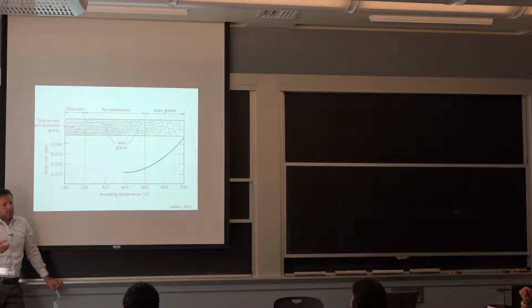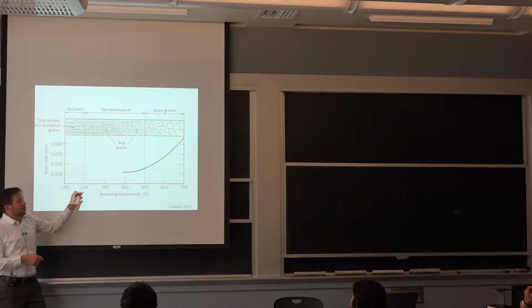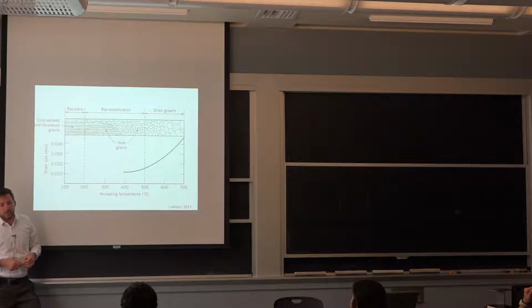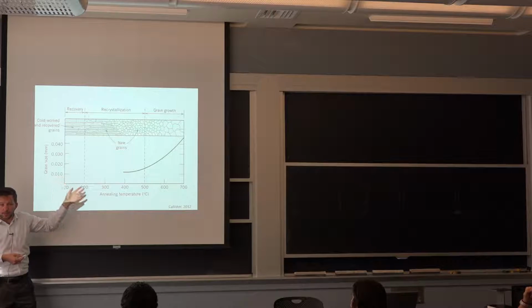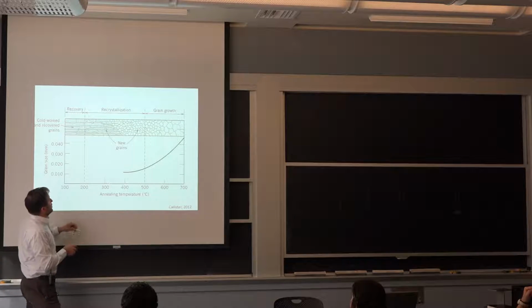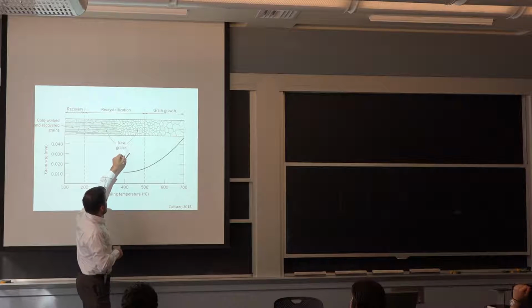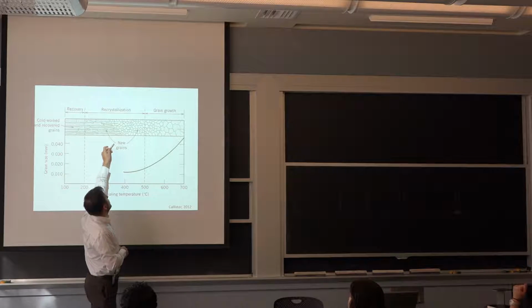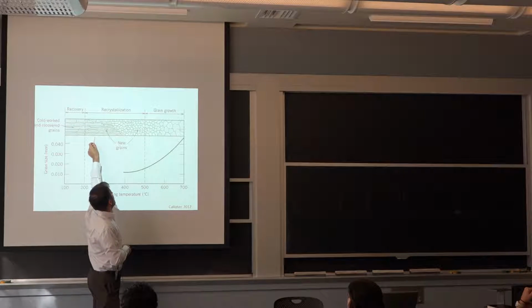But the example I circulated, where we could feel the roughness of the tensile dogbone, was a case where some grains grew much bigger than the others. So anomalous grain growth can happen if you're heating too fast or you're heating too slowly. So there is essentially an ideal range of temperature and deformation rate where all the deformed grain turns into new, smaller grains.